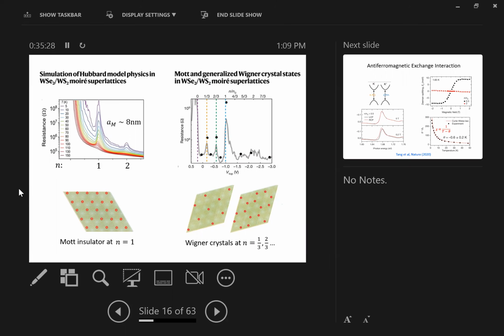Yes. These are STMs. These are the cartoons, but they are STMs. Back then it was only done in some kind of transport and optical experiments. They could say that there are insulating states at 1/3 and 2/3 filling, and then the conjecture, which is very reasonable, is that these are just this kind of Wigner crystal states. And since then, Feng Wang's group at Berkeley has done STM measurements. They literally see this kind of charge order pattern.